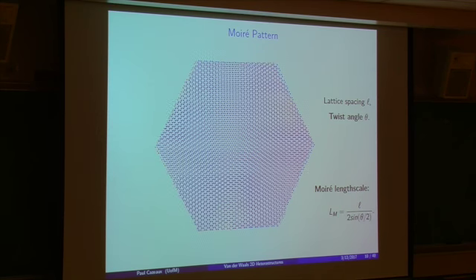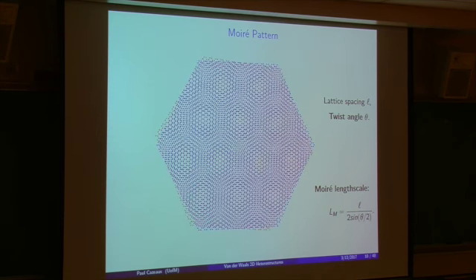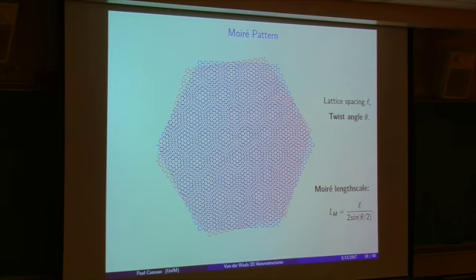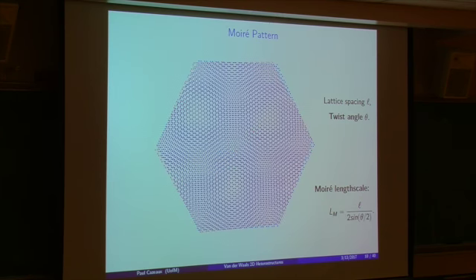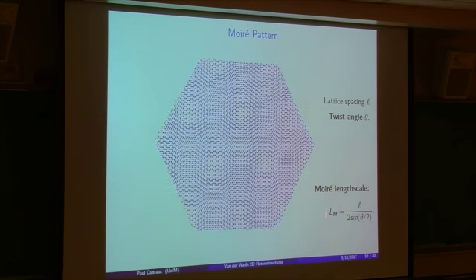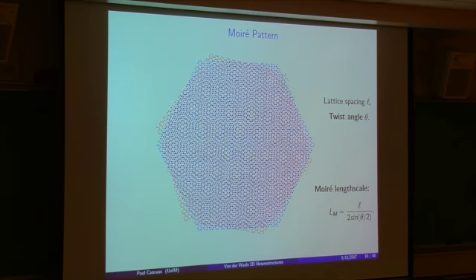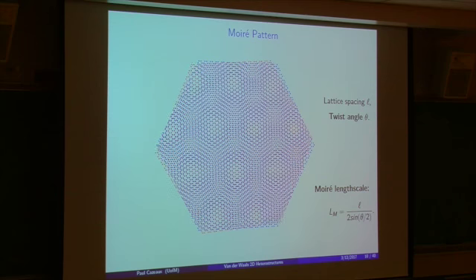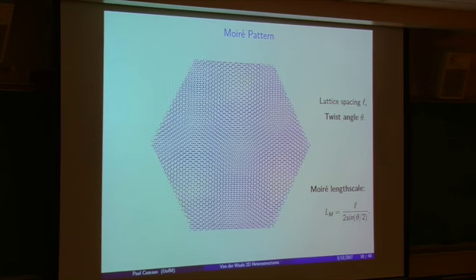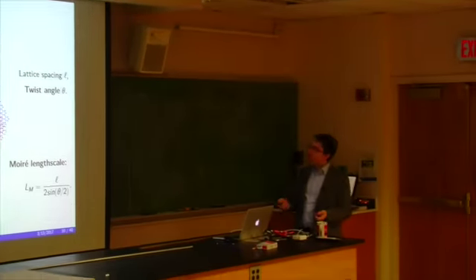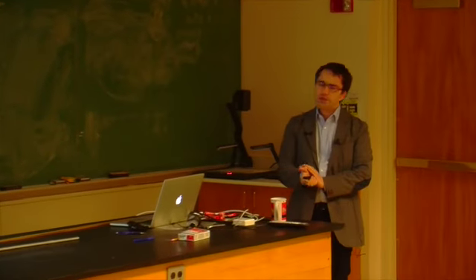So with this mechanism, we can produce structures that are quasi-periodic, almost periodic, on a very large scale. At this scale, if we think about 0.1, 0.2 degrees, then we can really reach gigantic, not quite periodic, but quasi-periodic domains. How do we understand this?